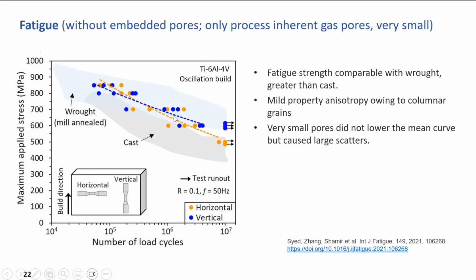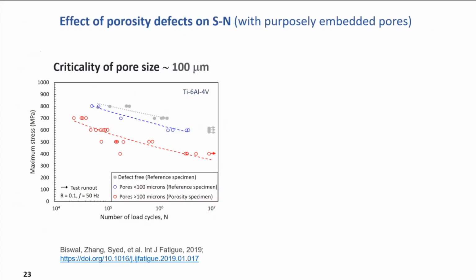And there's very mild anisotropy because of the columnar grains, so one direction is different from the other direction. But because titanium grains are very fine, the anisotropy is much, much milder than steels. I have seen papers on steels where the anisotropy is very strong. So very, very small pores did not reduce the mean curve, but they probably caused the large scatter in the data. I can elaborate on this a little bit later after I talk about purposely embedded pores.